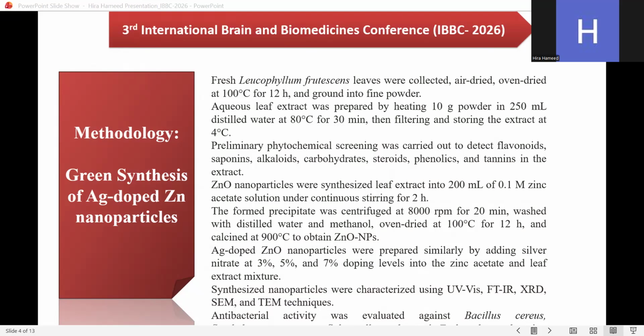Silver doped zinc oxide nanoparticles were prepared similarly by adding silver nitrate at different percentages, 3%, 5%, and 7% doping levels, into the zinc acetate and leaf extract mixture. Synthesized nanoparticles were characterized using UV-visible, FTIR, XRD, SEM, and TEM techniques.